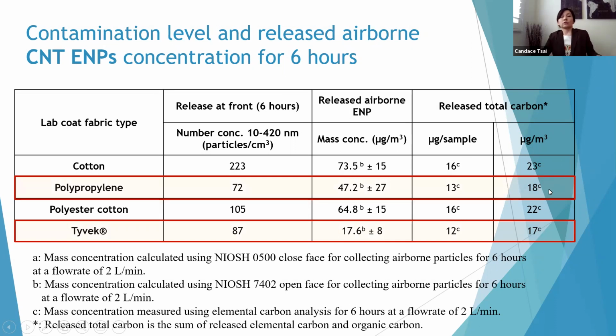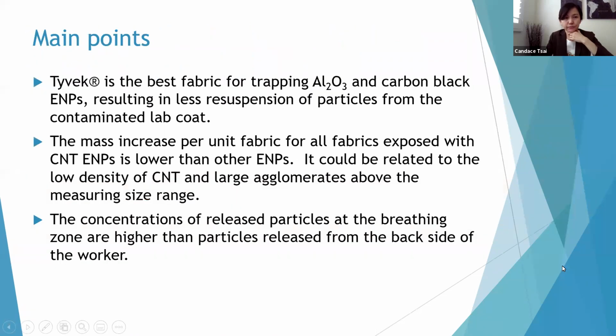To let you know, in this experiment, when we contaminate the lab coat, we can barely see the contamination because they are so small. And because the mass is very low, but because they are small particles, we can just see some black dots, just a little bit. But when we shake it for 6 hours, we can see them come up with concentration that way exceeds the current recommended exposure limit.